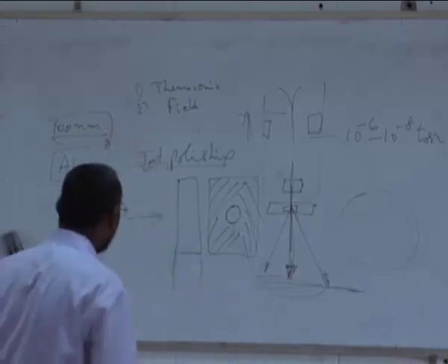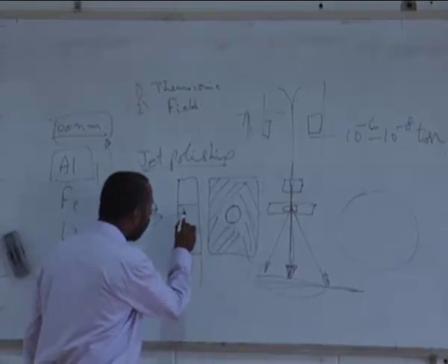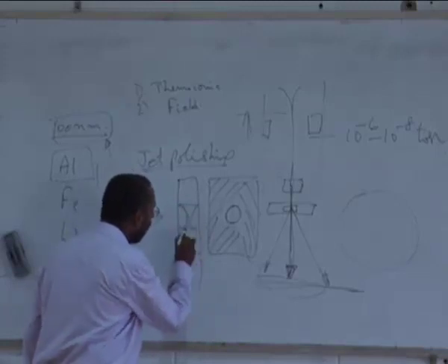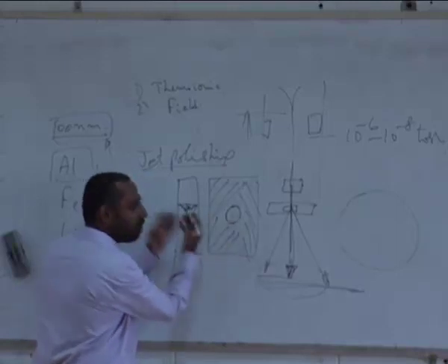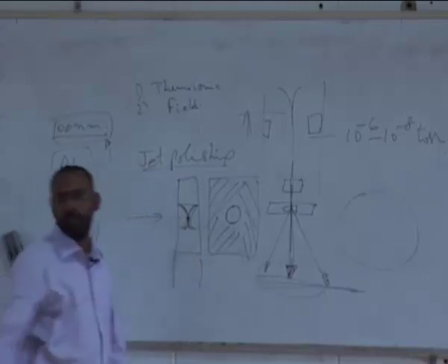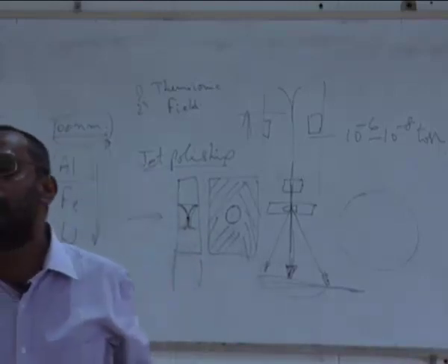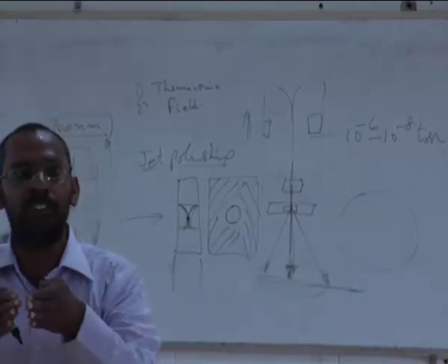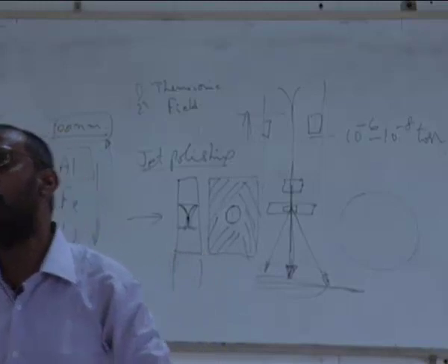When it starts dissolving, let's say it is this region which is exposed, and it starts dissolving slowly. When you hold it vertically in that liquid, you will see that from both sides the dissolution starts happening. As the dissolution progresses, at the center a small hole is formed.